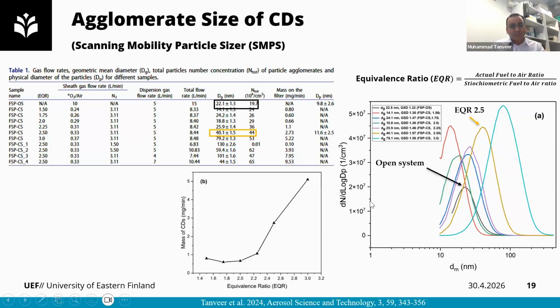For this, we have used an open system, as I mentioned earlier, and a closed system. For the closed system, we have used different equivalence ratios to tune the combustion condition. Equivalence ratio is basically the actual fuel to air ratio relative to the stoichiometric fuel to air ratio. So this defines the oxygen-deficient environment in the system, so that we can produce the carbon structure there, and by raising the EQR value, we can change the particle size and its morphology.